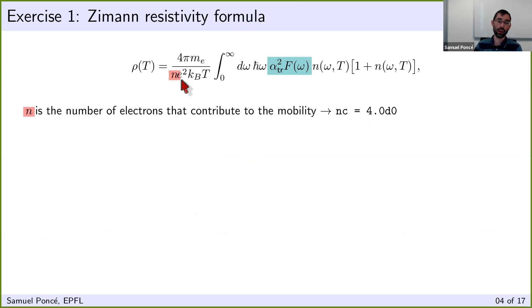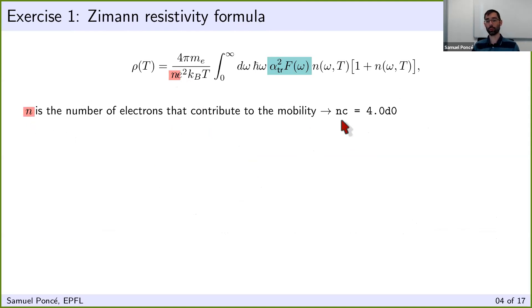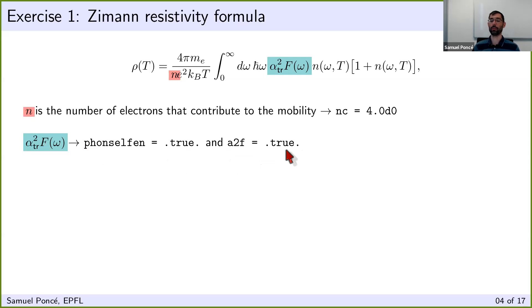For each element in the formula I'll point to input variables in the EPW code — you can download the hands-on and everything will be explained there. The parameter n is the number of electrons contributing to mobility, defined with the nc parameter — for lead it's four, but it depends on the material. To obtain the transport alpha-squared-F function, you set phonon self-energy calculation to true and alpha_sq_F to true, which will produce the spectral function and phonon self-energy.